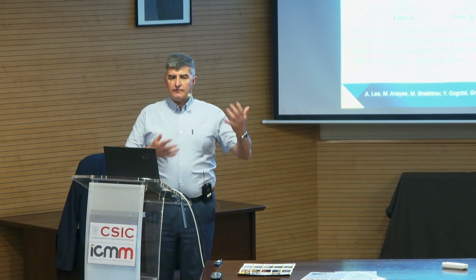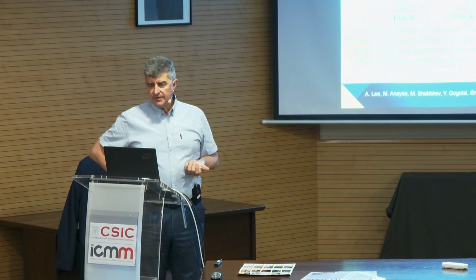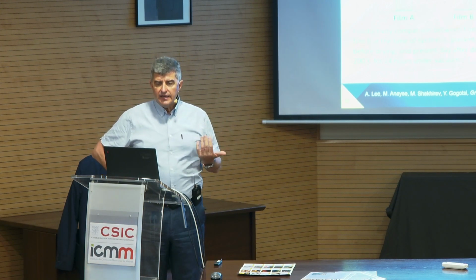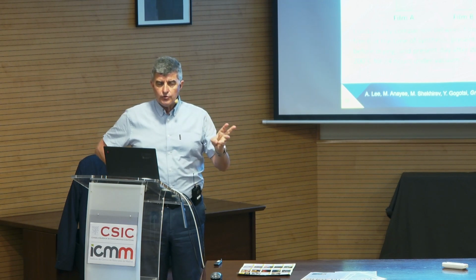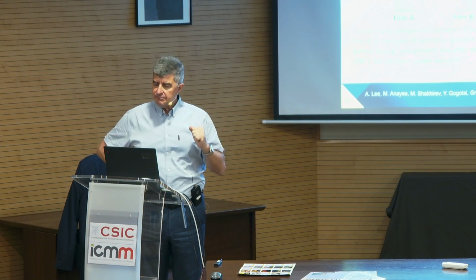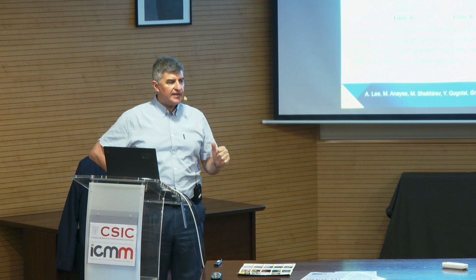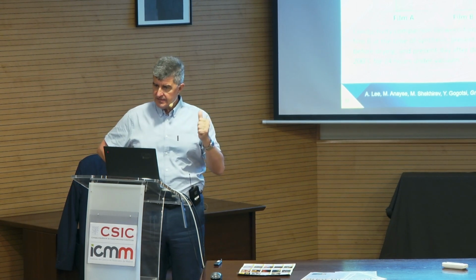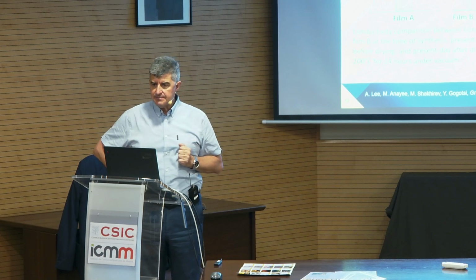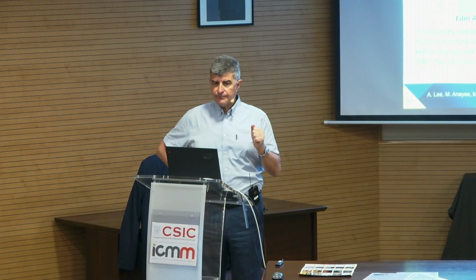As you see from a very large number of biomedical publications here, clearly for at least titanium carbide, niobium carbides, molybdenum carbides, tantalum carbides, there have been quite extensive studies on cytotoxicity and blood compatibility. There have been some studies on environmental toxicity on zebrafish. MXenes so far have not shown signs of toxicity.